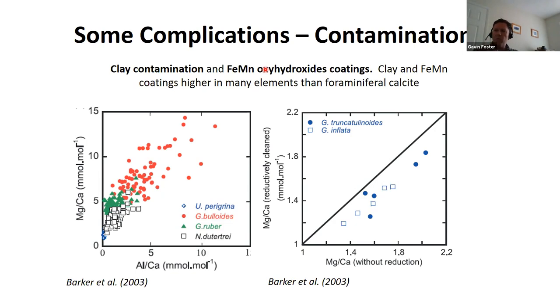especially when they're sitting at the top of the water column within the upper parts of the sediment column. They start getting this coating with the iron manganese oxyhydroxides. And that actually is enriched in magnesium, but it's also very enriched in rare earths and other elements. So with traditional methods using bulk dissolution of hundreds of shells, you do a reductive clean. You clean off this coating, which is laborious, and you end up losing some of the foram sample that you've separated, and it can actually change the ratio in an unexpected kind of way. So reductive cleaning is possible, so we can clean off these coatings.